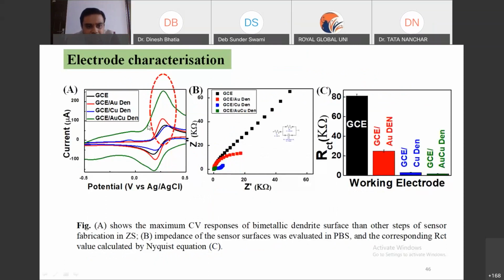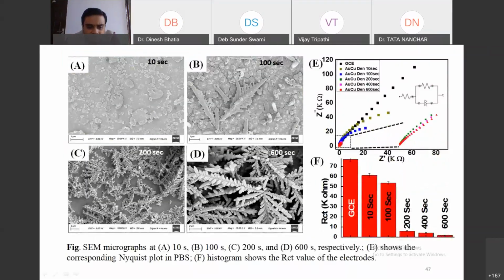You can see very clearly this is the bare electrode, the black one. But when we engineered the gold and copper together, the signal is maximum in this case. That's why I have circled this part. And complementary to this, the resistance of the surface having both the gold and copper dendrite is the least. It means the highest electron transfer. So these are the pattern structures as I've shown earlier, but this is for copper and gold both. And this is also the optimization time I have shown earlier, from 10 seconds to 600 seconds. Until 600 seconds, the maximum three-dimensional structure has been formed on the surface of the chip.